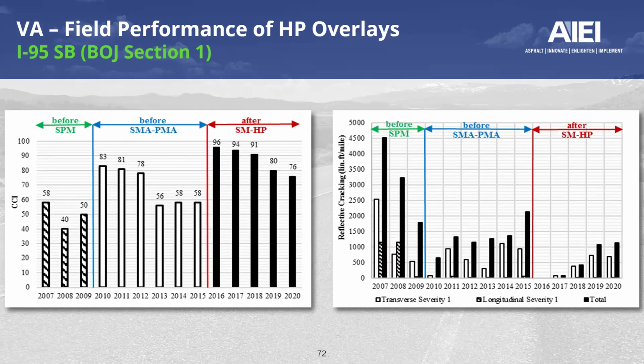You can collect all kinds of distresses. Since reflective cracking was the major distress of interest for this project, you will notice that the amount of reflective cracking was significantly lower for the HP section compared to the PMA section, and the rate at which the reflective cracking is increasing is much slower and much lower compared to PMA.